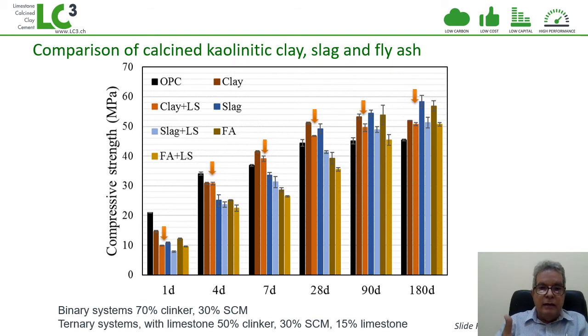Meaning, even at 4 days, before 7 days, we have very, very good strength results, and these materials can comply with the properties or the demand for a CEM I 42.5. And the performance is much better than any of the other pozzolans that we had used in the past, like fly ash, like slag, anything.